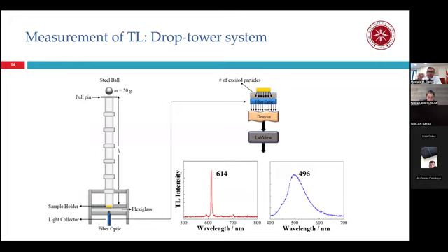The lifetime of this emission is very short, okay? So we have to establish a system to measure the spectrum. We have a cross-section of this setup, you see on the left-hand side. We have a black box made of polymethyl methacrylate. On the black box, we have a tower of 10 centimeter transparent cylinders, so we can make a tower. On top of the tower, we have a steel ball. We know its weight, so we release the ball from this height.